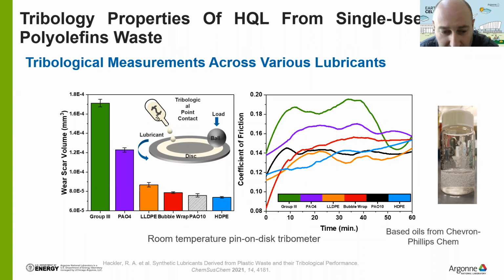lubricant oil? And what they did was look at what they call the pin-on-disc tribometer, looking at the wear scar, and we compare against group 3. The group 3 is the oil that comes from refinery, from distillation of crude oil, compared to the PAO, polyalpha olefin. In this plot, I report polyalpha olefin 2, 4 and 10. If you go to Jiffy Lube and you change your oil, and they ask you, do you want the mineral oil or the synthetic oil? The group 3 is the mineral oil. The polyalpha olefin is the synthetic oil.